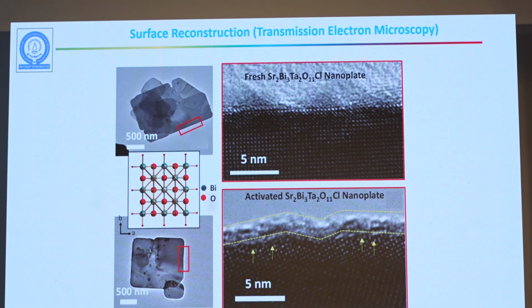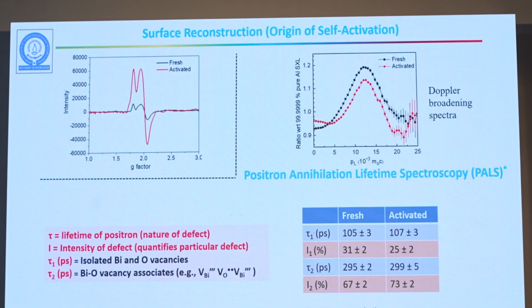is coming out. All right, and then the final thing I want to emphasize is that when these metals and oxygen come out from the surface, initially we can assume that they form defects on the surface. But these defects are very complex. These defects, they have a society. They don't stay all alone. They sometimes come together and form clusters.